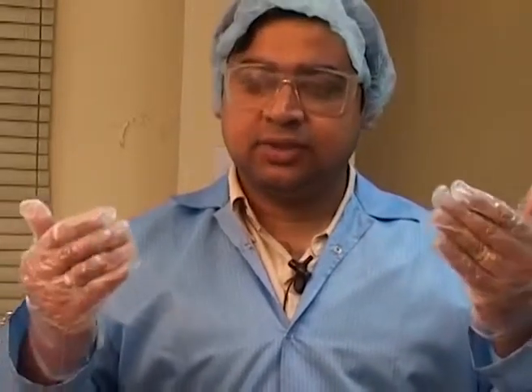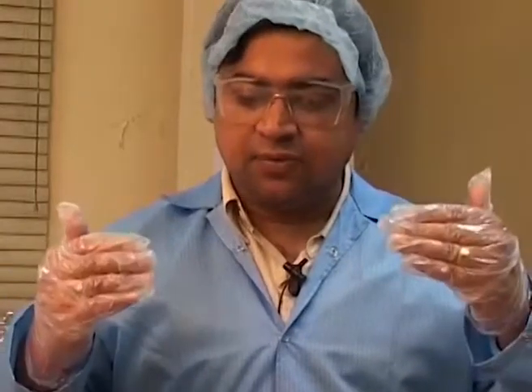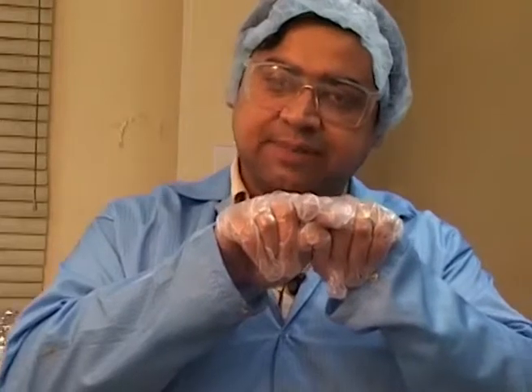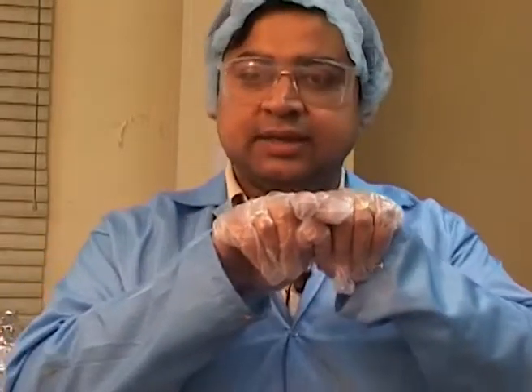You can develop a thin film of metal onto such a resist and then remove the areas where the resist was cross bonded or unbonded or remaining. Therefore, when that resist comes off, it takes off the metal also, and in the places of the vias or trenches or capillaries which you have opened in between, where the silicon was exposed, the metal stays back, and you can use this technique for developing thin interconnects on chips, especially in microelectronic chips.